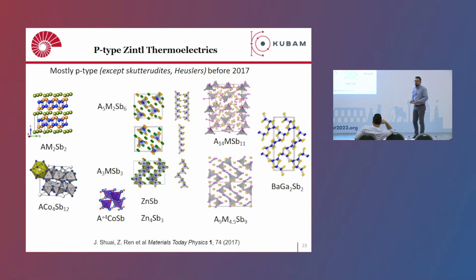So most of these materials inherently show p-type properties. So 1-2-2, 5-2-6, 3-1-3, 14-1-11, 1-2-2, they inherently show p-type behavior because of these cation vacancies. Generally, when you make them, you observe that there is a very stable defect in the structure, which is a cationic defect, okay? Calcium, magnesium, or whatever. They show inherently p-type behavior.